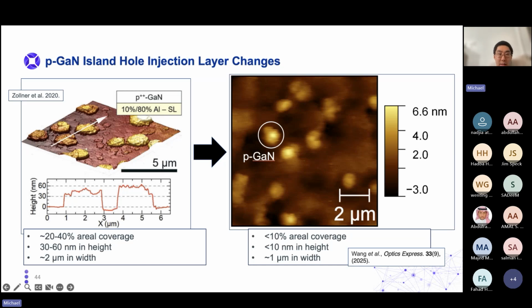do not grow in the same way because of the likely smaller lattice constant at the top of the surface due to less tensile stress in the material. With the small lattice constant, the gallium nitride should nucleate less easily, which results in these smaller islands, which are 10% aerial coverage versus 20 to 40% in our old work. Less than 10 nanometers in height versus 30 to 60 nanometers in height in our old work, and about 1 micron in width versus 2 microns in width.